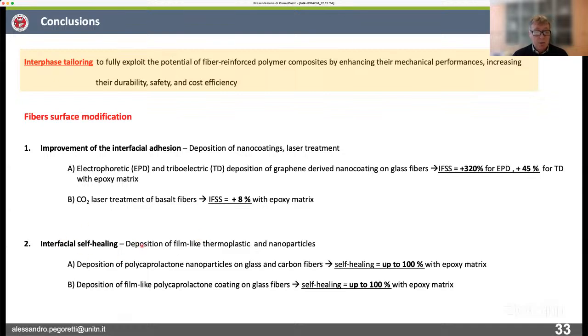In the second part, we use a thermoplastic material deposit on the fibers, both glass and carbon fibers, in form of either thermoplastic nanoparticles or a continuous film of thermoplastic material. The material we select was polycaprolactone, and we did observe that it is possible to heal the interface, to repair the interface up to 100% in case of carbon fiber. And basically, we also reach 100% with glass fiber by using, in this case, a film rather than nanoparticles on the surface.